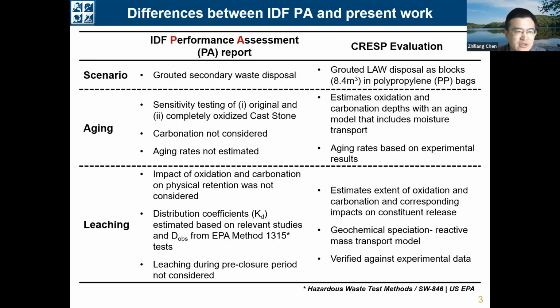The modeling scenario in the report is for the grouted liquid secondary waste, while the modeling scenario in this work is for the grouted primary low activity waste containing polypropylene bags. And for the aging of the cast stone in the report, the cast stone is assumed either in reduced form or in completely oxidized form, and the carbonation was not considered in the report, and also the aging rates were not estimated. While in this work, we developed an aging model to estimate oxidation and carbonation depths along with the aging times. And also the aging rates were derived based on some experimental results.